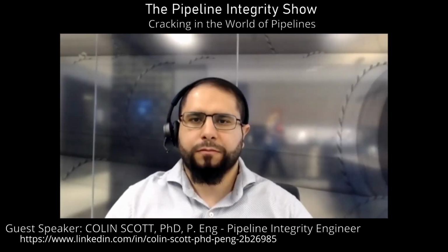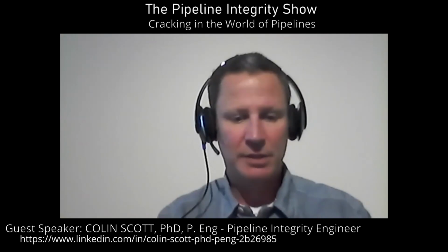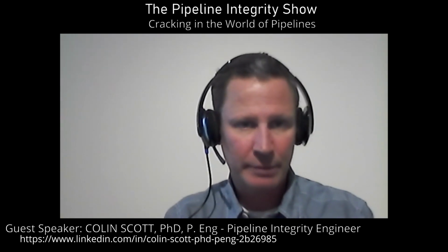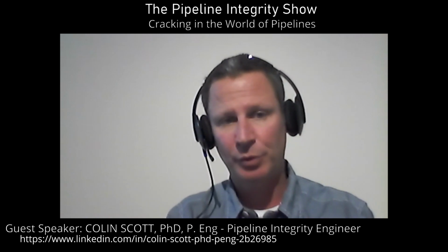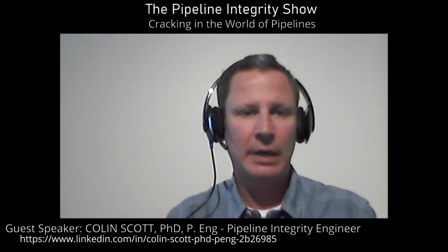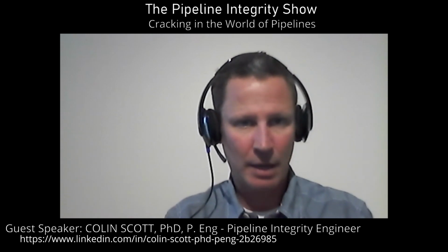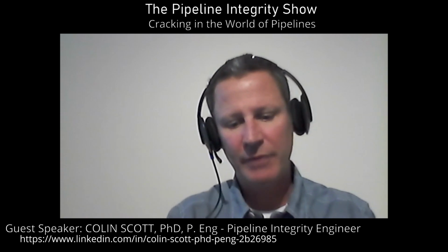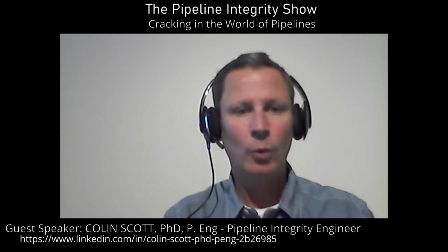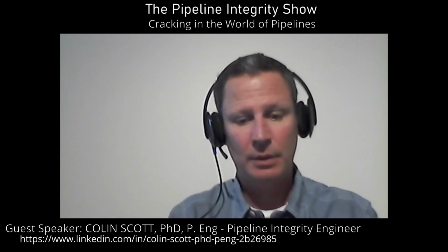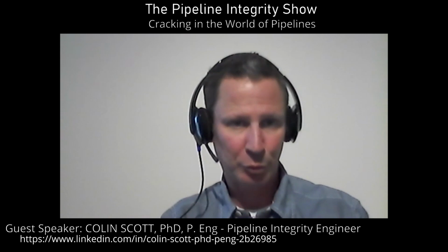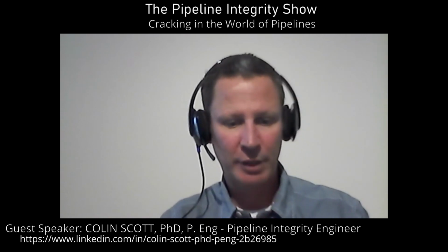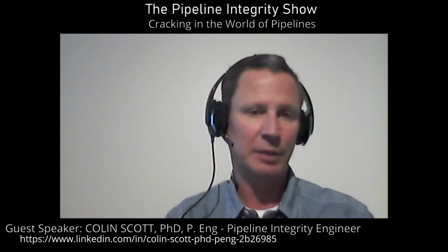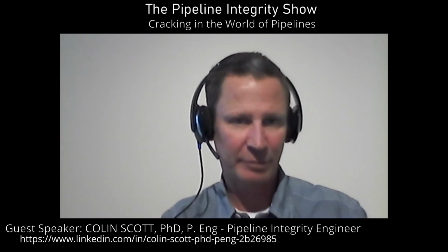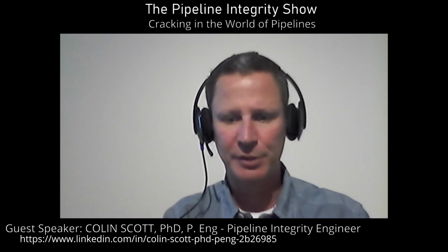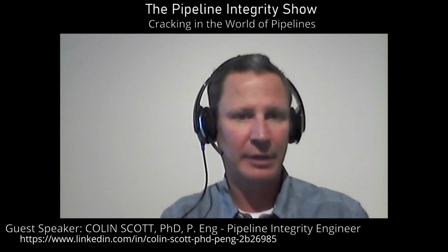Mm-hmm. Sure. Generally, what happens with crack management programs is at some point, either through a hydro test program that's used for integrity management or an inline inspection tool program for integrity management, we're going to have to figure out how many cracks we have in the line and how deep they are and how long they are and how they're distributed. And once we've got that information, or we've got some assumptions about that information, we're going to use one of the various crack assessment models to calculate what is a predicted failure pressure. We want to make sure that our maximum operating pressure is always going to be lower than that, and we're typically going to put in a safety factor. In Canada, 25%. In the US, they work with some different numbers. So it's really important to be able to come up with a failure prediction model.